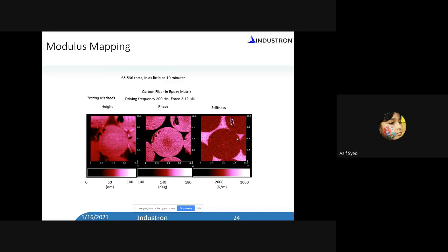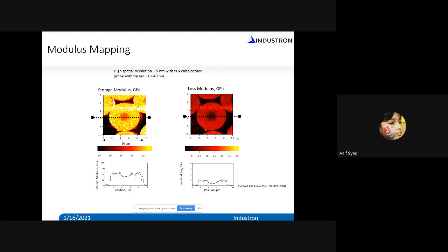You do the modulation and then scan on the surface. And this is for a fiber epoxy composite. And with that map, you can go and measure the storage and loss modulus as an image. This is a fiber epoxy composite. You can see the fiber has a different modulus compared to the epoxy here outside. And you can do that storage as well as loss modulus.